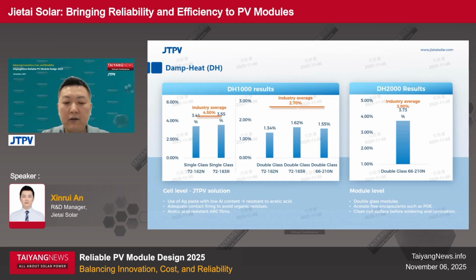But for module suppliers, our advice include using double glass modules, which inherently have less DH problems than single glass ones. And also acetate-free encapsulants such as POE is highly recommended, not only due to its superior DH, but also better PID performance than EVA. And finally, we should never neglect the importance of keeping a clean environment for module soldering and lamination. So the modules made of JTPV mono 1 cells show an excellent DH1000 results of about 3.5% for single glass and 1.5% for double glass modules, both far below the industrial average. Even with DH2000, our double glass modules are still well below the 5% IEC mark.